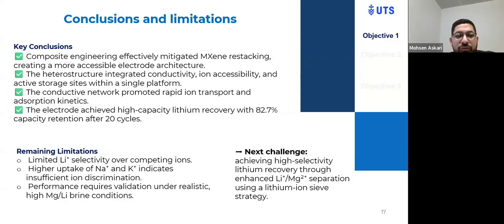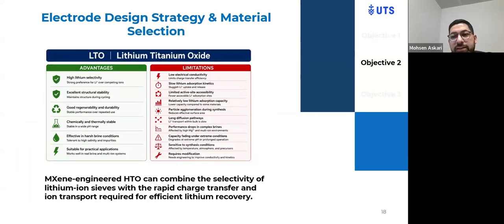But there are some remaining limitations. Limited lithium selectivity over competing ions, higher uptake of sodium and potassium indicate insufficient ion discrimination, and performance requires validation under realistic higher magnesium to lithium brine conditions. Based on these limitations, the next challenge is achieving high selectivity of lithium recovery through enhanced lithium to magnesium separation using a lithium ion sieve strategy. That is the target of the next objective.